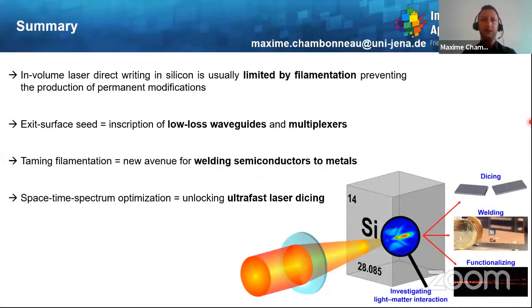as we have seen, in-volume laser direct writing inside silicon is usually limited by filamentation, which prevents the production of permanent modifications inside the material. However, if one uses exit surface seeds, like crater production at the exit surface of the sample, it is possible to perform laser inscription of low-loss waveguides and multiplexers inside the material.